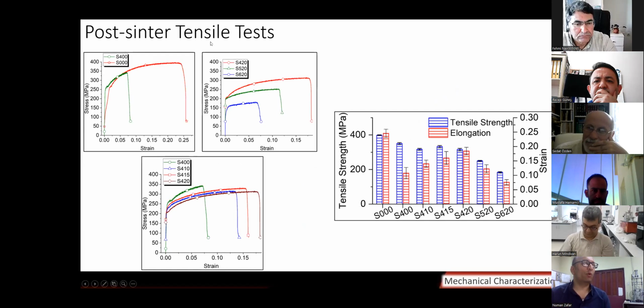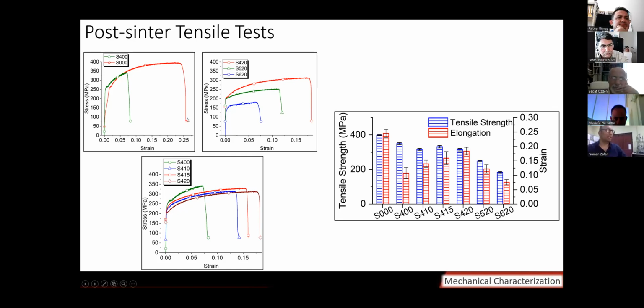Here is the comparison of post-sinter tensile behavior. The presence of the core has significantly influenced the tensile behavior in the post-sinter state more than it did in the pre-sinter state. There is an overwhelming decrease in the strain and also a considerable decrease in the tensile strength of the S400 specimen. But I want to also tell you that this was just like a needle, a 1 millimeter needle, or maybe 1 millimeter wire, 1.5 millimeter wire, which has no discontinuities, no reinforcement, no core, nothing. You try to pull it, and it will eventually break.